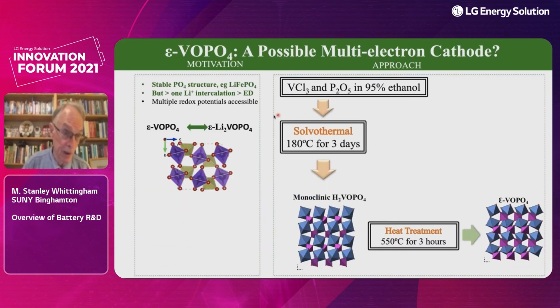It's a tunnel structure, so a very stable structure. It's not going to change structures readily as you put lithiums in and out. We hope to put 2 lithiums in there. After many years of struggles, we found a way of making this so it's electrochemically active.